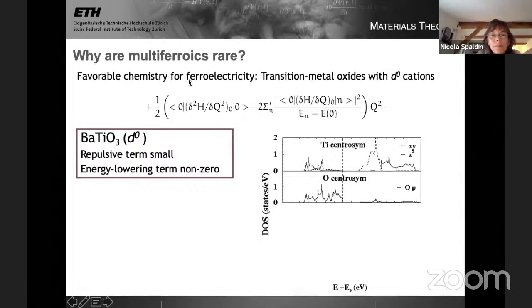So here I've written out these two terms again. The first term we'd like to be small, and of course this is going to be small if I don't have a lot of valence electrons, so that when I push the ions towards each other, there's not a lot of repulsion. So if I have a d0 electron density, then this first term is small. The second term is going to be very negative, and therefore favorable, if my ground state and my first excited state have different parity.